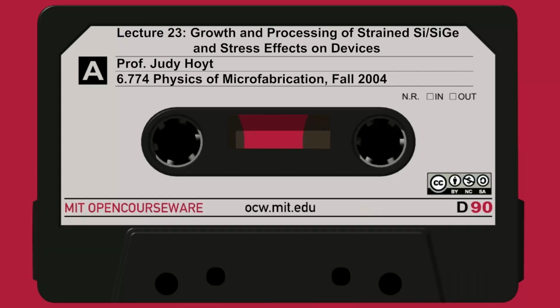But in the early 90s, there were breakthroughs on how to grow these layers, how to grow them at high enough temperature so the threading dislocations could run to the edge of the wafer, and how to grade the germanium content. So you start growing at silicon lattice, and then you gradually add germanium as you go up, and you grade it over many microns. It turns out when you do that, you can relax the silicon germanium, but you can reduce the number of dislocations that thread to the surface. All the dislocations run out to the edge of the wafer, where you don't care about them because you're not going to make any devices at the edge of the wafer.